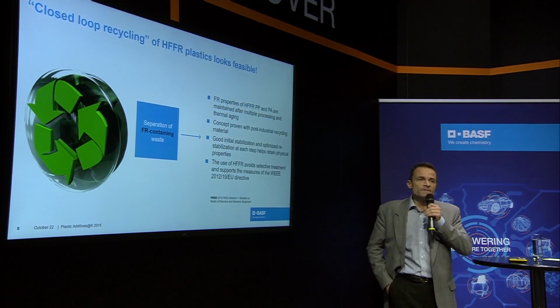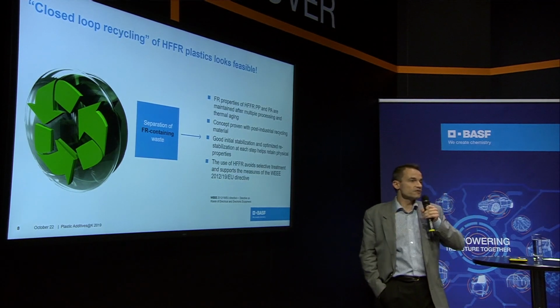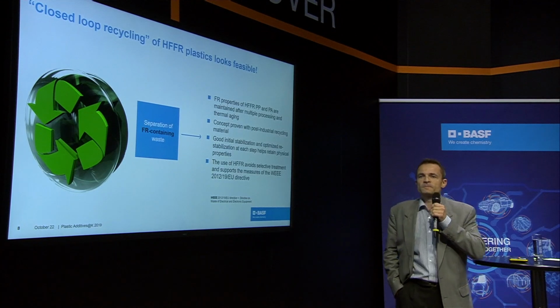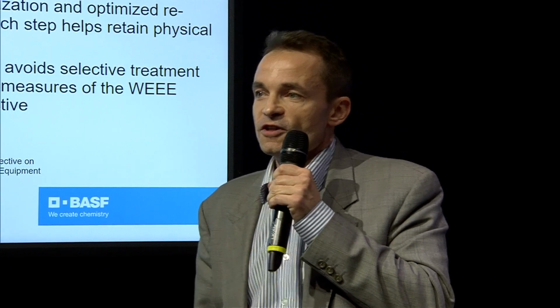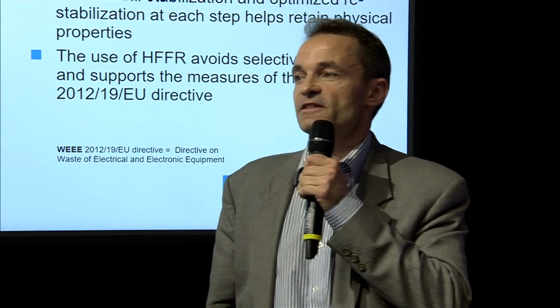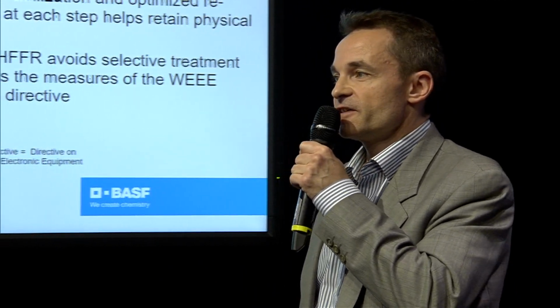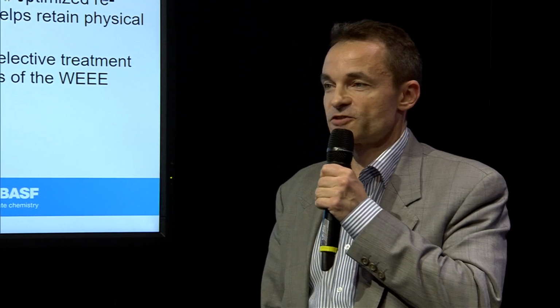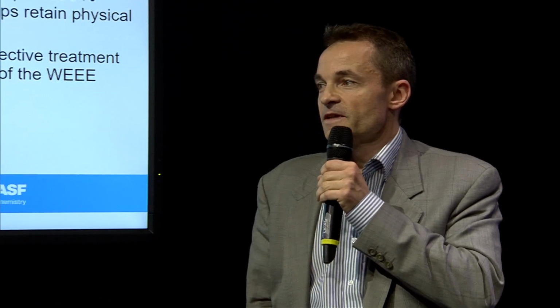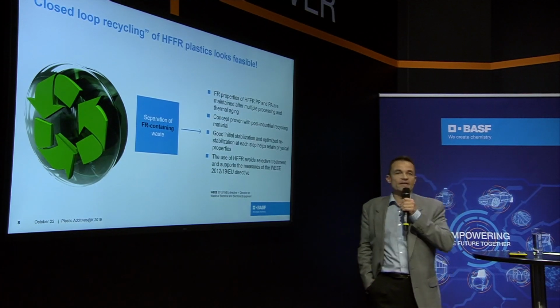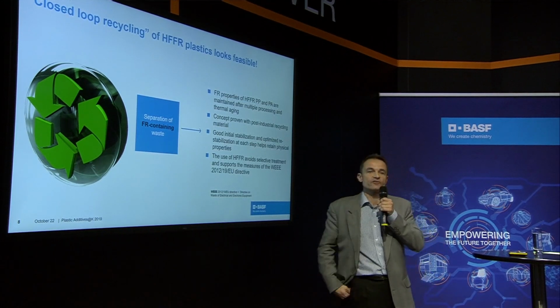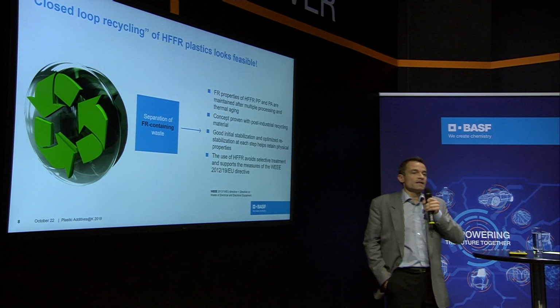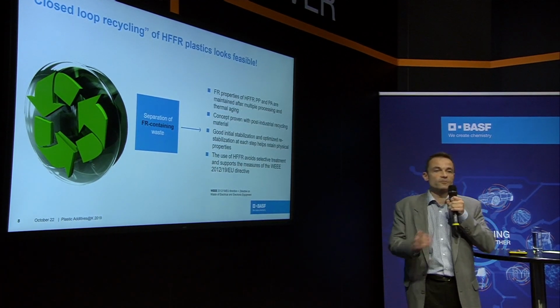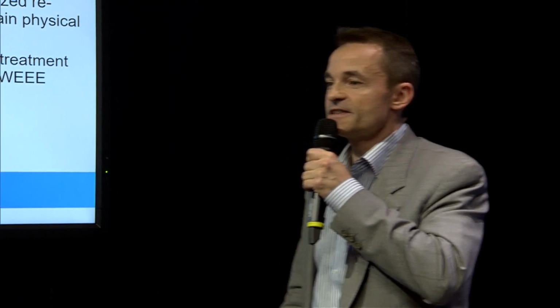So finally, it appears that halogen-free flame-retardant polymers contribute to mechanical recycling. It was demonstrated that the flame-retardant performance, either of polypropylene plus Flamestab NOR116 or of polyamide 6 plus melamine cyanurate, is maintained over multiple extrusion and over oven aging. In the case of polyamide 6, we could also see that it was valid for post-industrial scrap. In addition, it's known that antioxidant provides good stabilization, and this was also validated in this study.